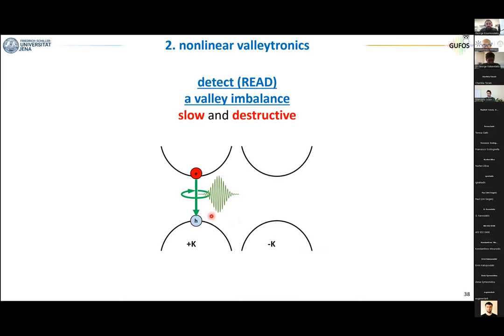a photoluminescence. So those of you, I know George, who is working with valleytronics, you typically measure photoluminescence. That means you generate a valley imbalance, so you put excitons only in one valley, and then you wait for this exciton to recombine and check if the emitted luminescence is equally polarized. Now, this method is not the ideal one because this method is slow. You have to wait for the recombination and it's destructive. The moment that you emit light, the valley information is lost.